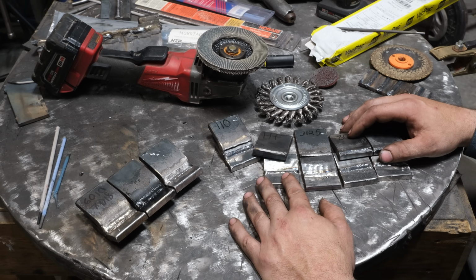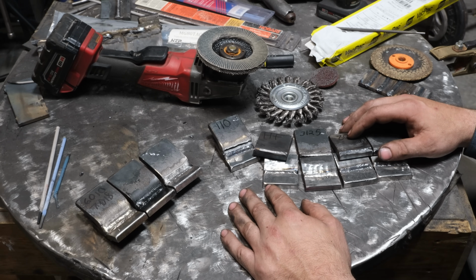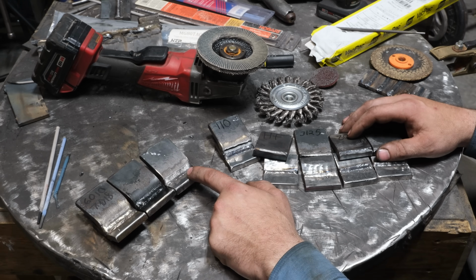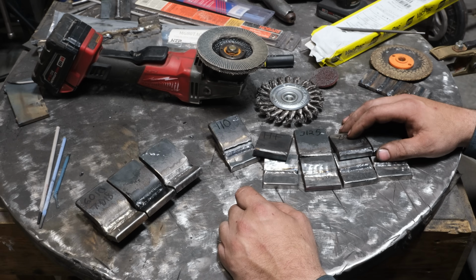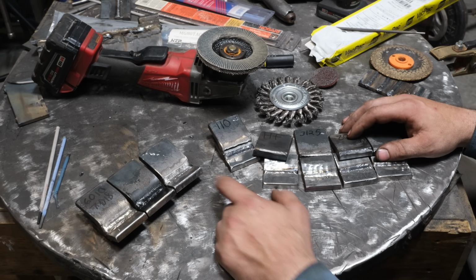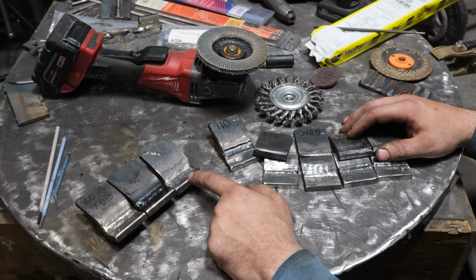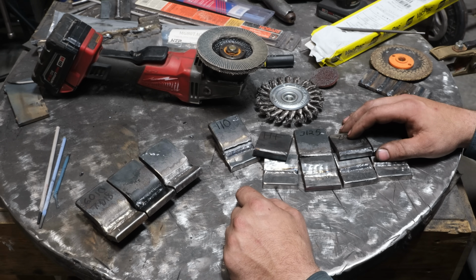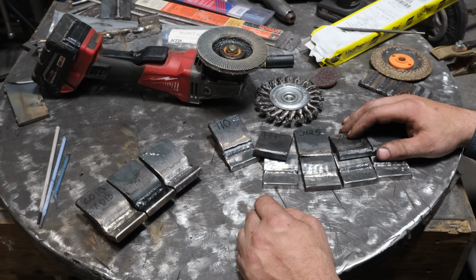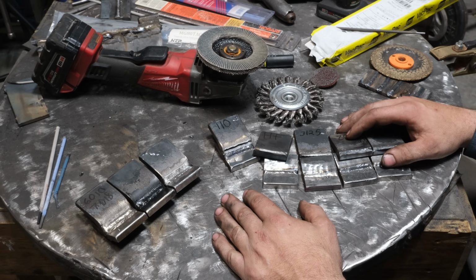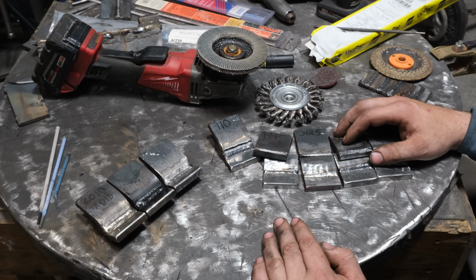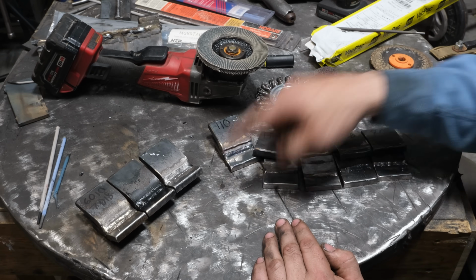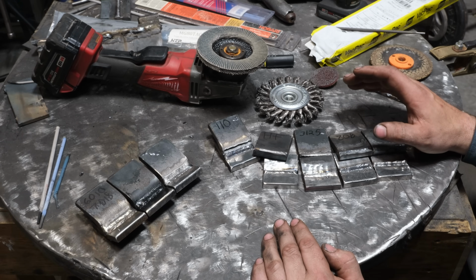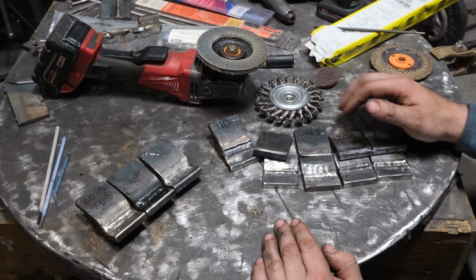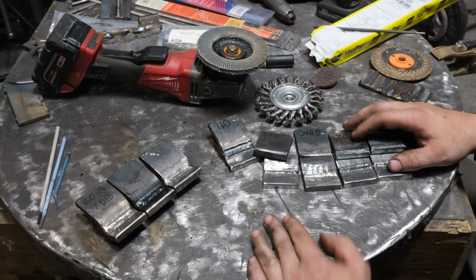Now, had I done this test with 3/8 high strength steel, then I have a feeling that we would start seeing the issue of ductility and lack of strength on these being an issue, because the weld would fail long before the material ever would, and we would be able to maximize the stress on that weld. And the difference in that case of how much weight something could hold using the right rod would be huge. Not to mention, depending on what you're welding, like if you were welding high carbon steel as a repair, 312 stainless would last far longer than any ER70 or 7018 material. And that's because it doesn't become brittle with the carbon absorption. All things to consider, I guess.